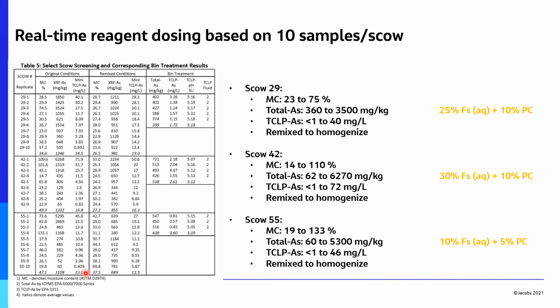This was more of a semi-consolidated material, even though some of the moisture contents were actually a little bit higher. What we were able to do with this one was hit this with 10% ferric sulfate and 5% Portland, which was our preferred blend for the semi-consolidated material. And again, that was a pass.